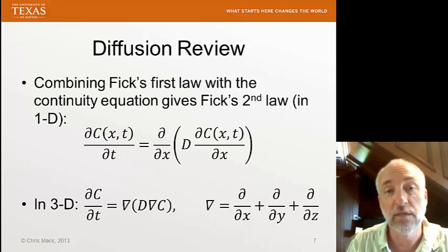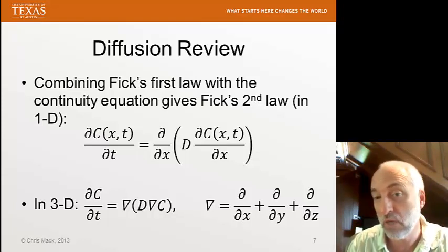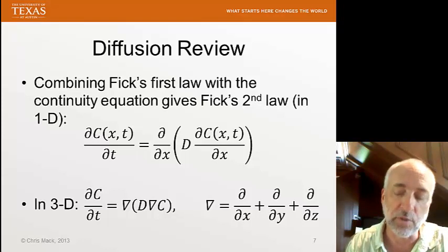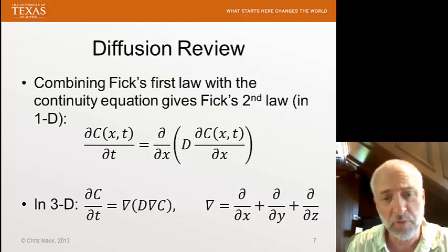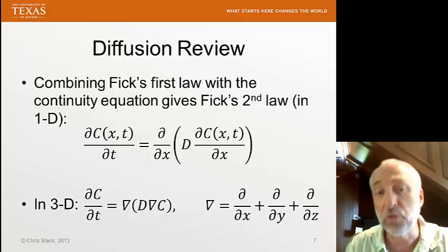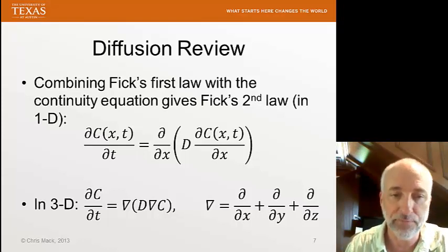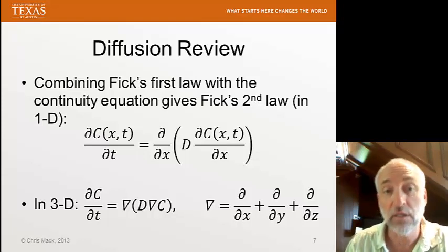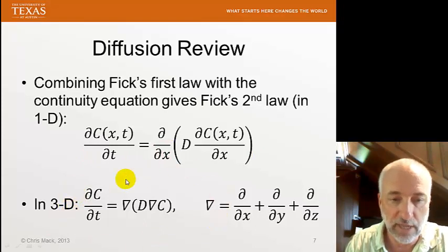If we combine Fick's first law with the continuity equation, we get Fick's second law. We take the derivative of Fick's first law with respect to X and substitute it into the continuity equation to get Fick's second law, which is shown here. In one dimension, the concentration is a function of X and time T. In three dimensions, it would be a function of X, Y, and Z, and we show what that equation looks like using the del operator as shorthand notation — the del operator is simply d/dx + d/dy + d/dz.